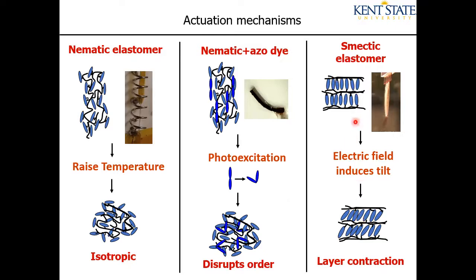This particular electric field response is driven by a tilting. So this is a smectic phase, but it has a susceptibility to tilt under an electric field. That's called the electroclinic effect. And when you tilt it, just like library books on the shelf, when they tilt to one side, they get shorter in this direction, wider in that direction. So does the polymer, and that drives deformation. So you get a layer contraction in thickness and a width expansion. But because of the way it's glued and because of its shape and maybe a little bit of asymmetry between the way the front and the back of the material is responding, it also makes it twist. But in any case, that's why it moves. It's because the electric field induces tilt. So those are three ways to actuate our artificial muscle.